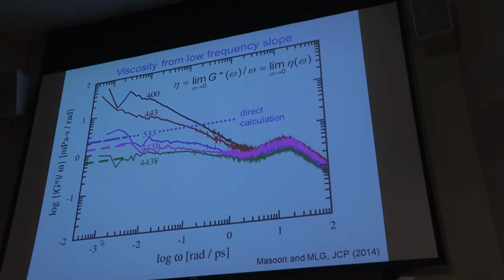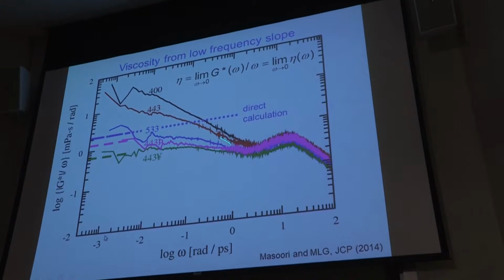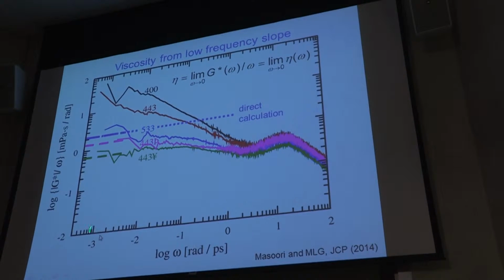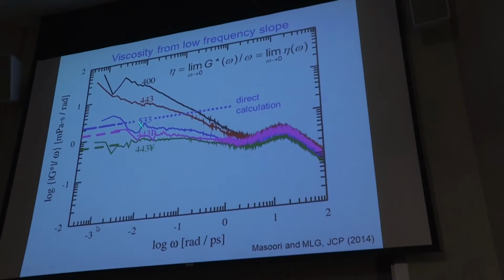We can also use this to get an estimate of the viscosity. This is a particular curve that would show a plateau. Even though we're at very, very high frequencies, at the highest temperature, we're starting to see some evidence of a plateau. A different viscosity calculation happens to lead to this estimate, so we're happy about this. It also shows that at lower temperatures, we can't really make an estimate of the viscosity because this curve is still going up and we're not reaching a plateau in it.